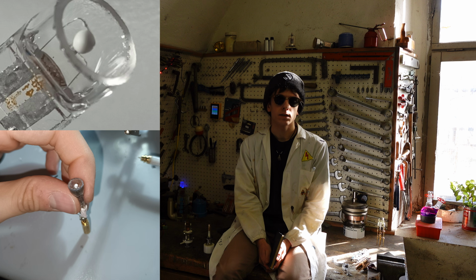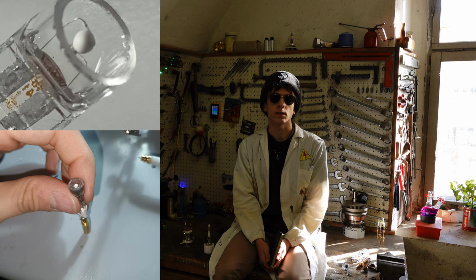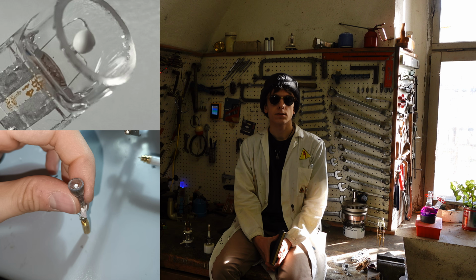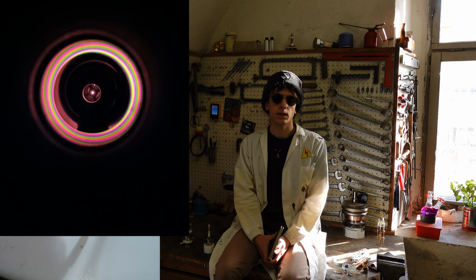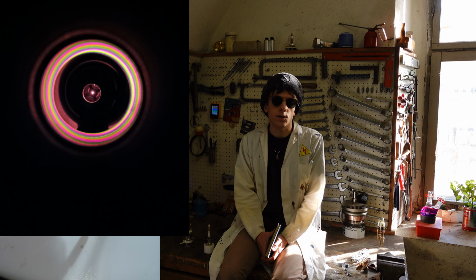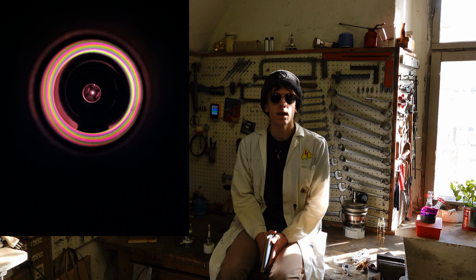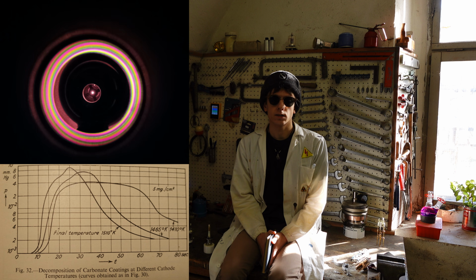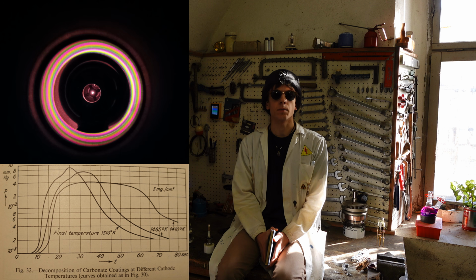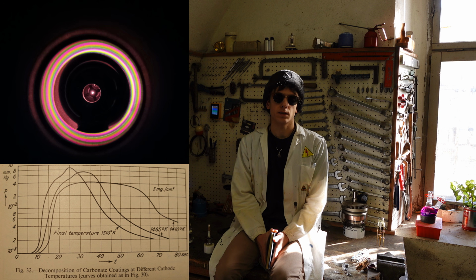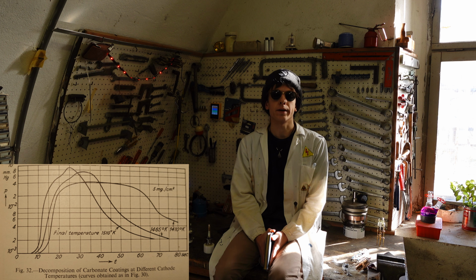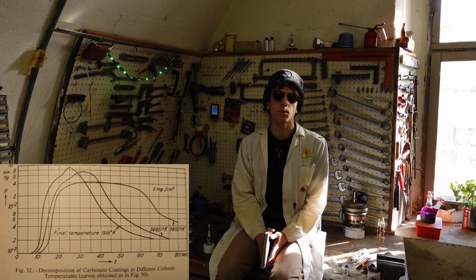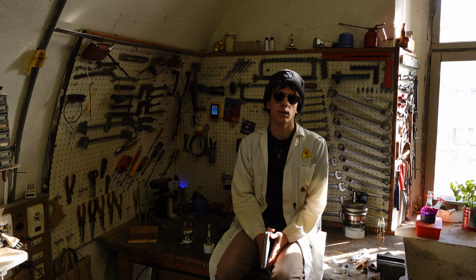After that, the filament covered in strontium carbonate was inserted into the vacuum chamber, and after reaching the maximum vacuum, the filament was heated red hot by the current flowing. The emission increases as the activation proceeds. Unfortunately, it is really hard to measure temperature inside this type of system, and one would need an optical pyrometer. Activation is also aided by drawing some current from the tube, as the electrons emitted probably help in reducing the oxide, shortening activation time.